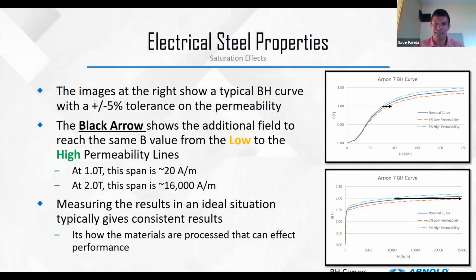So if we take a look at a nominal curve over here for our material properties, and then we take a plus or minus 5%, so let's take maybe a minimum and a maximum curve for that silicon steel. At 1 Tesla, a very low saturation, and probably closer to no saturation, the difference between the low curve and the high permeability line, at a fixed output field or fixed flux density, the field to excite that output field, the difference is about 20 amps per meter. So not really that big of a difference, even if our properties aren't as good as the nominal values.